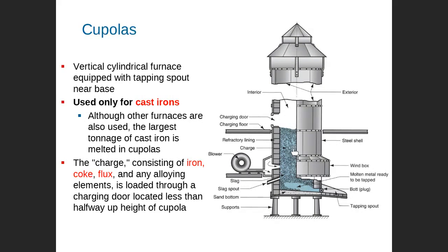And this coke is basically carbon. We cannot use coke with other materials like aluminium or copper. If you try to use coke with other material, not cast iron, like aluminium or copper, it will become an impurity.